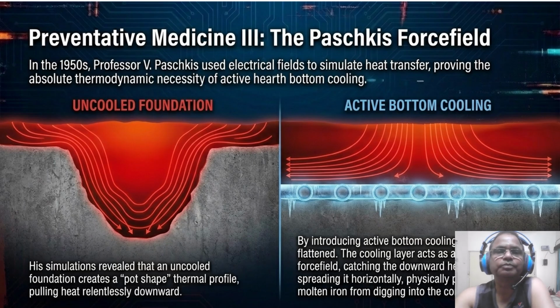So now in the 1950s, Professor Paschkis used an electrical field to prove the thermodynamic necessity of active hearth bottom cooling. On the left, an uncooled foundation creates a pot-shaped thermal profile, pushing heat relentlessly downward. So now look at the right, active bottom cooling by introducing cooling pipes. The isotherms are flattened. The cooling layer acts as a thermodynamic force field, catching the downward heat flux and spreading it horizontally. This physically prevents the molten iron from ever having the thermal energy to dig into concrete.